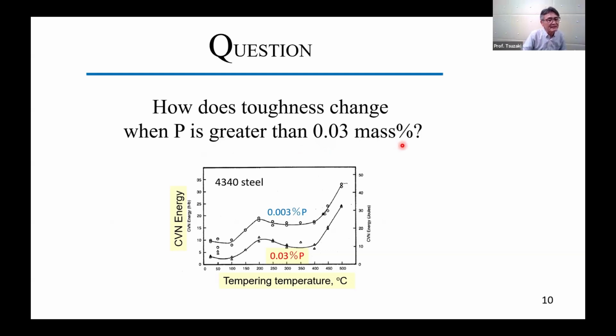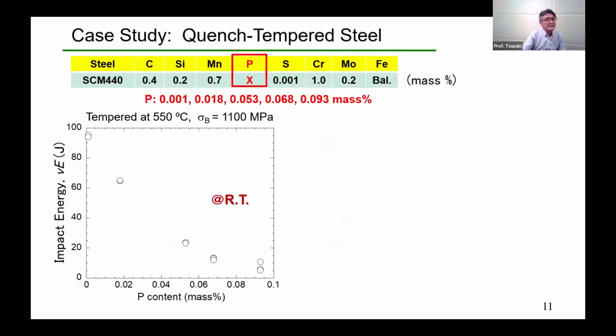I wanted to know the result for high temperature tempering above 500 degrees Celsius, where the impact energy rises. I believe you all would like to know too. So I did. Here is the result. Only phosphorus content was varied in SCM 440. The tempering temperature in this case was 550 degrees Celsius, and the tensile strength was 1100 MPa.